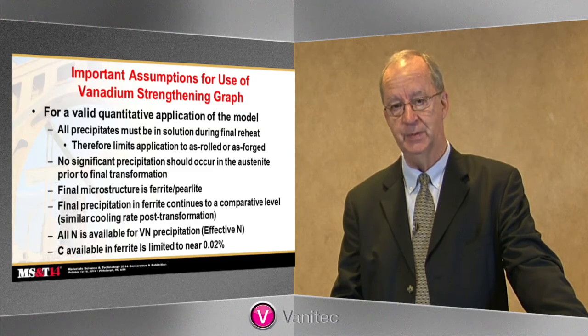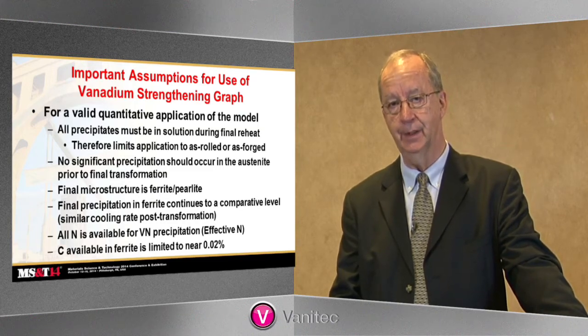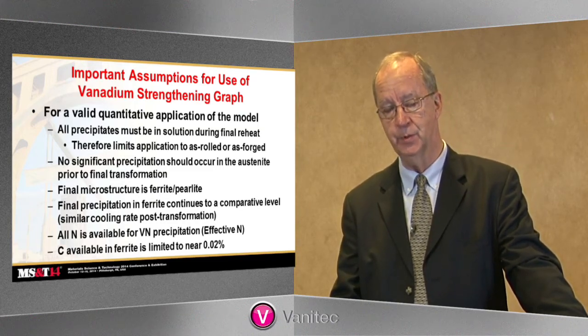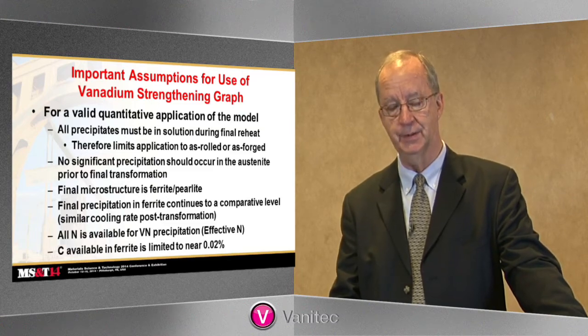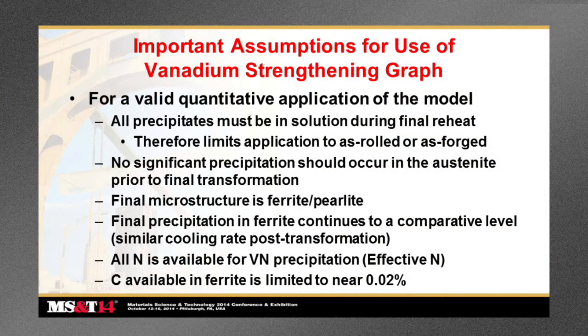So when you normalize material, you can't expect to get the kind of response from vanadium nitrogen precipitation strengthening as we see in this model. It pretty much limits the model to use in as-rolled or as-forged conditions. But that is primarily where microalloying is used. So it's really not an issue, you just have to be aware of that. And also, no significant precipitation should occur in the austenite prior to final transformation to be able to get this precipitation strengthening. The final microstructure is a ferrite-pearlite microstructure.